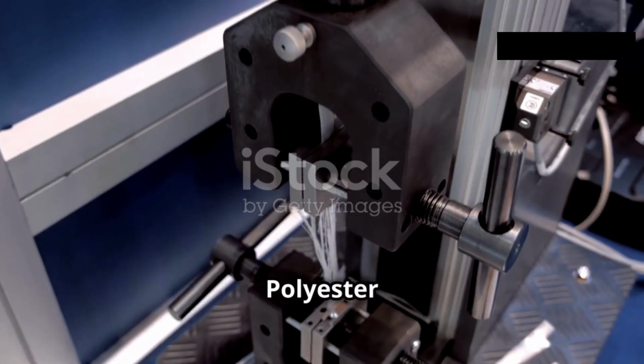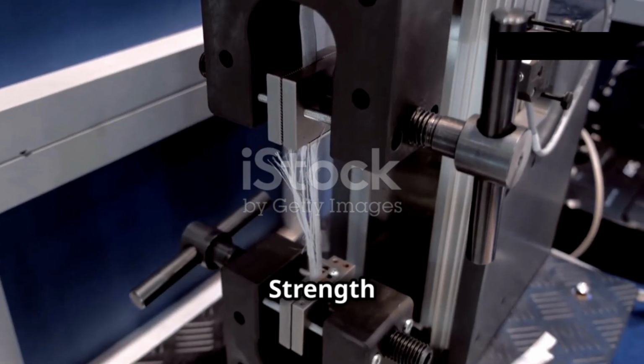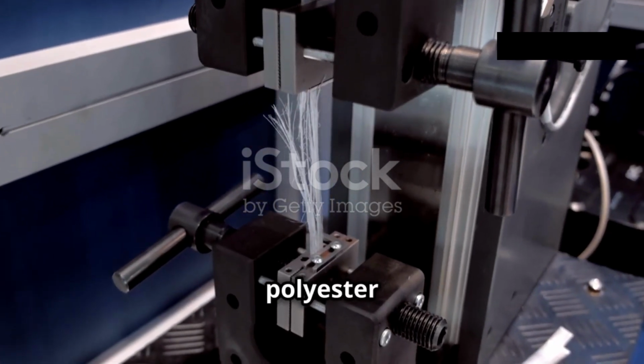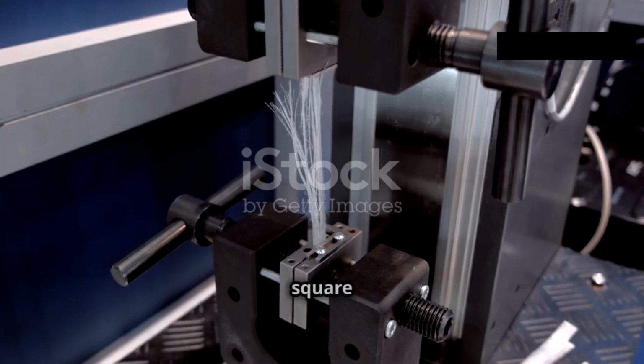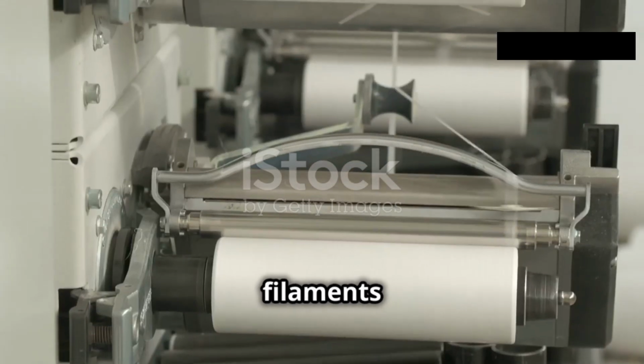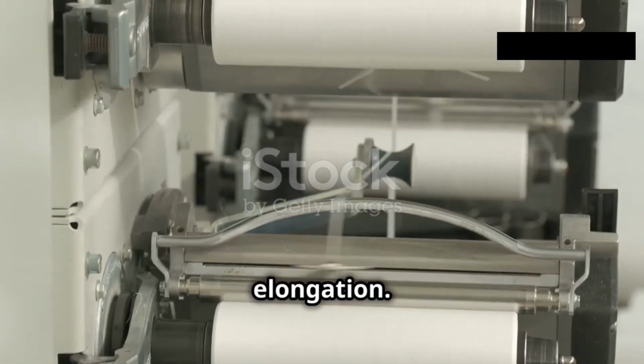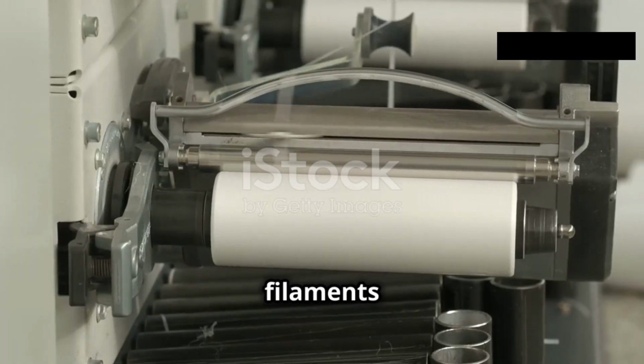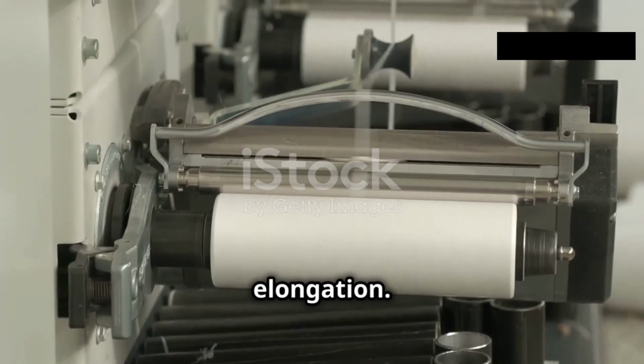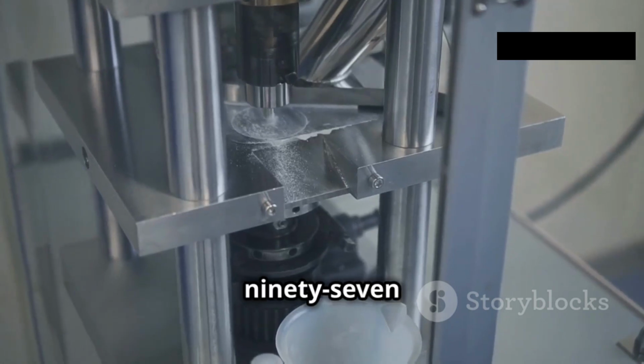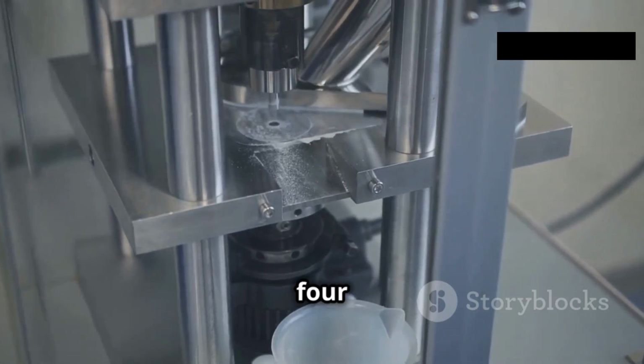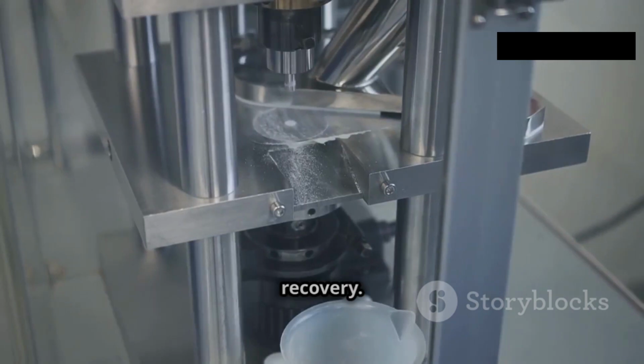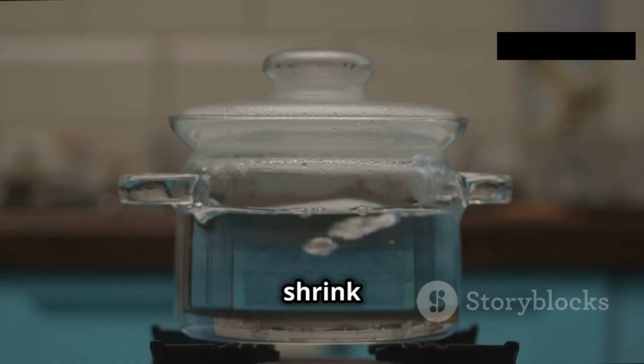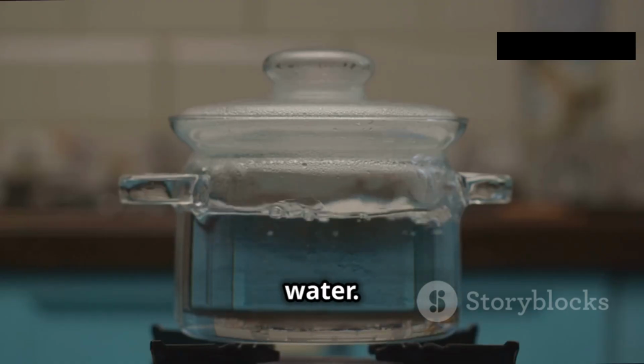The properties of polyester fibers include a tensile strength of medium tenacity, polyester filament at 80,000 pounds per square inch. High tenacity filaments have 8 to 11% elongation. Regular tenacity filaments have 15 to 20% elongation. At 2% stretch, it has 97% recovery, and at 4% stretch, it has 90% recovery. Polyester fabrics shrink 7 to 10% in boiling water.